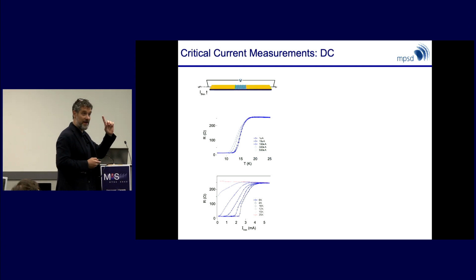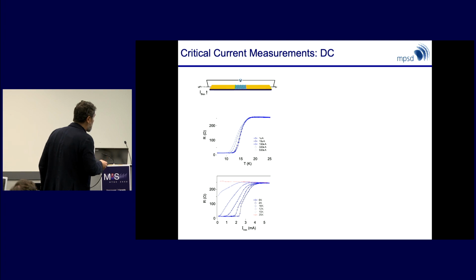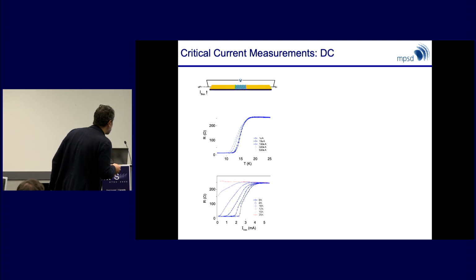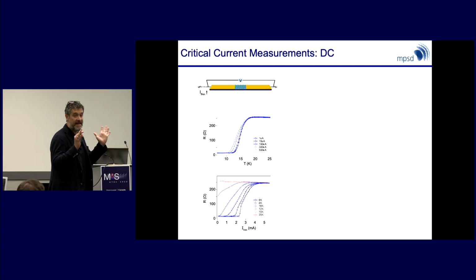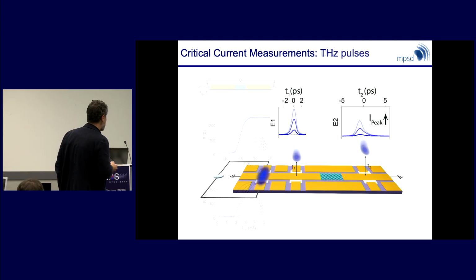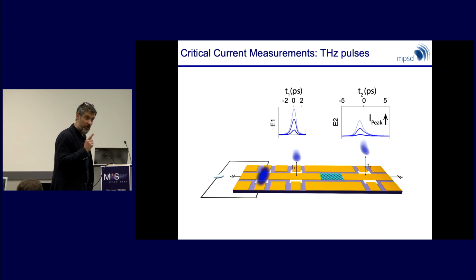Right, critical current measurements. This is the equilibrium critical current measurement. Those of you that do superconductivity are used to these curves. The critical current, these are integrated currents, is of order a few 10 kiloamps per square centimeter. These are non-equilibrium critical current measurements with the terahertz pulses.